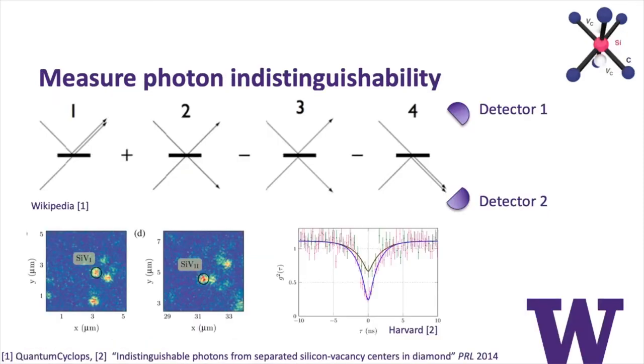And then before I talked about how we want the spectrum of the emitted photons to be Fourier transform limited to the lifetime of the emission or the wave packet. There's actually a measurement that you can do to test this as well, not just lifetime measurements and spectral measurements. And this is by using, again, quantum mechanics. If you have two photons coming into a beam splitter, which transmits half the light and reflects half the light, there are four possible outcomes.